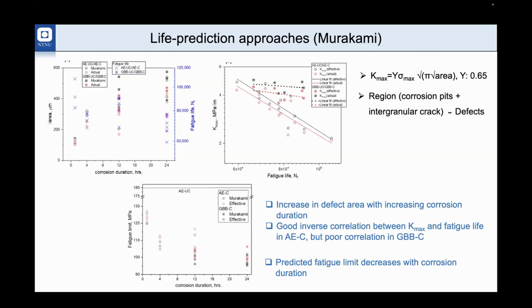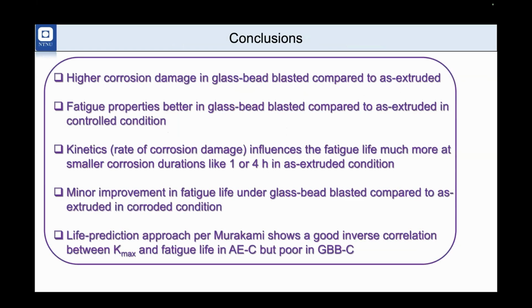And in the graph at the bottom, you can see that we also tried to predict the fatigue limit using the Murakami approach. This gives the life prediction based on the different durations of corrosion, and as expected, with an increase in corrosion duration, the fatigue limit decreases. So these are the main conclusions.